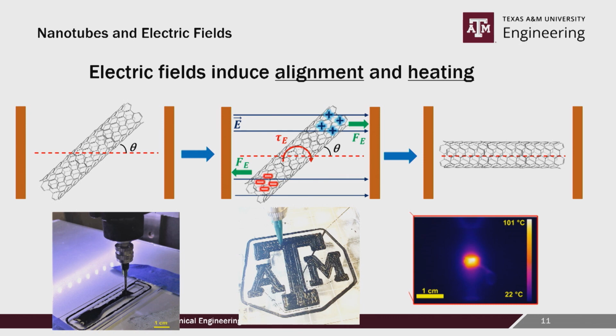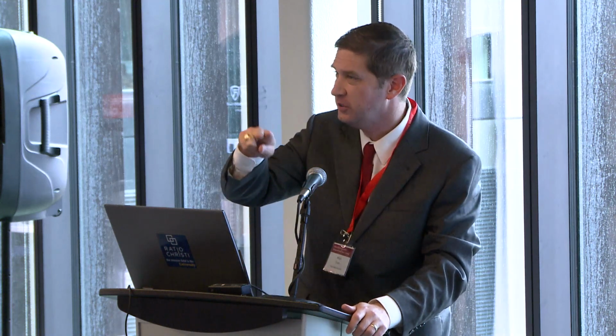It's like imagine trying to make a tower out of toothpaste, right? As you build the tower up, eventually it yields under its own weight. And even if you manage to get your tower of epoxy to hold, you go set it in the oven and you begin to heat it up to cure. And what happens to the viscosity as you heat it up? The viscosity goes down, then it begins to cure, and then it goes back up. So to get around those problems, we used electric fields, not just to align, but to heat these nanotubes so that as you print, it cures the resin. So instead of building this little tower and hoping to God that it doesn't fall down, you print a layer and then use the electric field, cure a layer, print, cure, print, cure, print, cure. And you can print virtually any thermosetting structure you can think of using that technique.